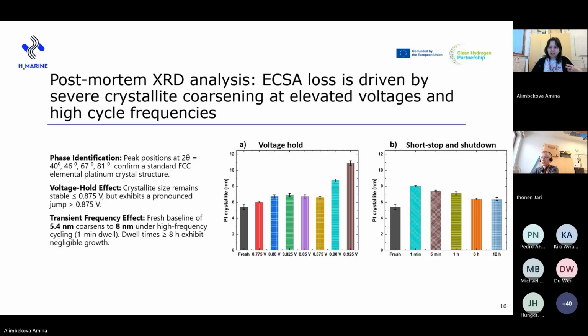Especially when looking at the short stop and shutdown AST data, the coarsening here is probably driven by Ostwald ripening, by the oxidation and reduction cycles, and it reduces as the amount of these cycles gets smaller and smaller.